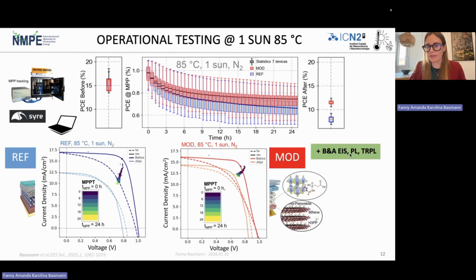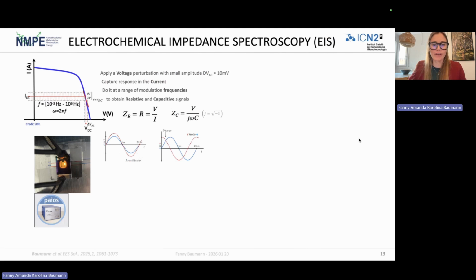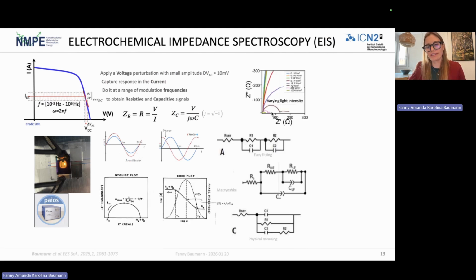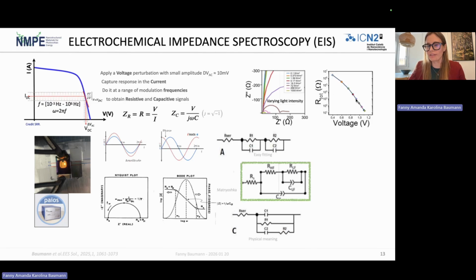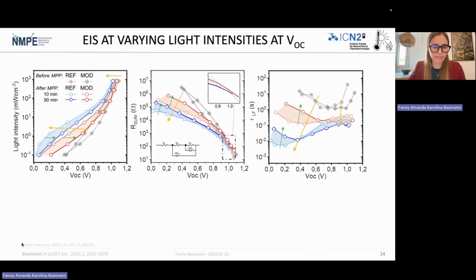Now we're going to look at this with the before and after characterization. So first we have impedance spectroscopy, which is done at varying light intensity. And these Nyquist and Bode plots are later fitted to this nested circuit, and we get something like this. So the parameters are compared to the open circuit voltage that is generated in each case. So during impedance measurement, we hold the cell around the open circuit voltage here. And then we can see different tendencies over time and depending on the degradation. In this study at 85 degrees, when we just look at the reference device and we see what tendencies we see over time, it can be found here.